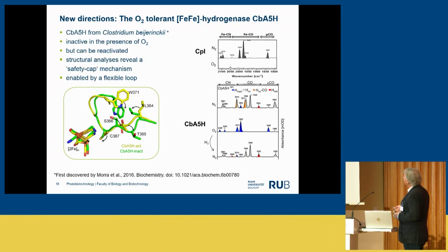If you do this with another enzyme from a Clostridium species, you recognize that under oxygen, you still see the bands, meaning the enzyme is still there. But you also recognize that there is a shift of this band to this band, and this means that under this condition, the enzyme is active, but under this condition is not active. So it's inactive in the presence of oxygen, but it can be reactivated, and this is very important, of course. So you can somehow store it under oxygen.